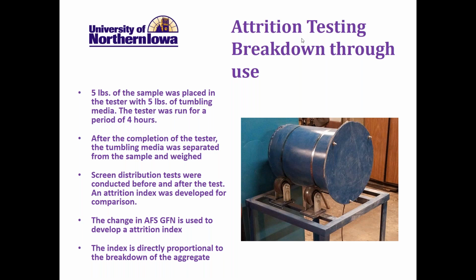One of the important points I want to bring up: it was brought up before that there would be performance advantages in using blends of ceramic and silica. And that oftentimes is true. Casting quality, casting surface can be improved. The issue with doing that is that the ceramic material has almost twice the hardness of some silica sands. So you can imagine using both of the materials in a system, a green sand system. The ceramic material will actually grind the silica into dust. So if the ultimate goal is reduction of respirable silica dust, this does not help. It actually increases the dust generation in a foundry.